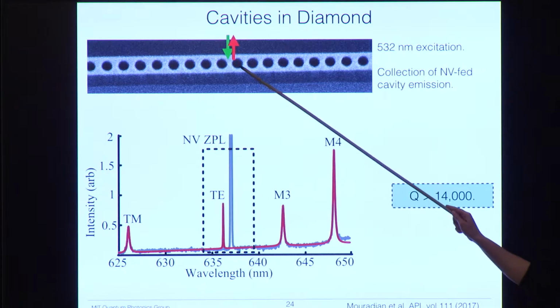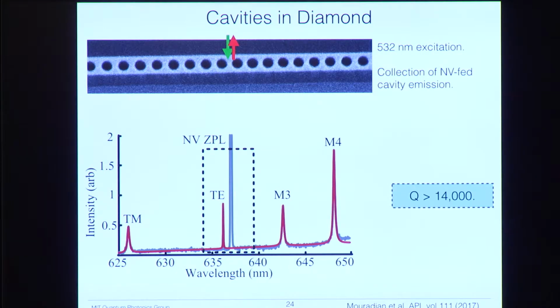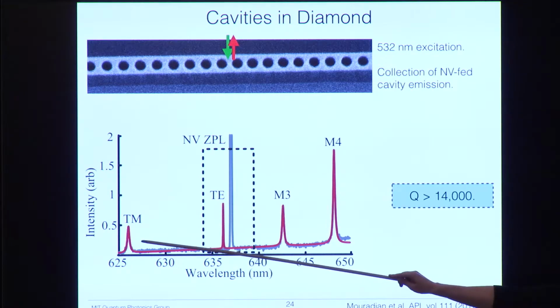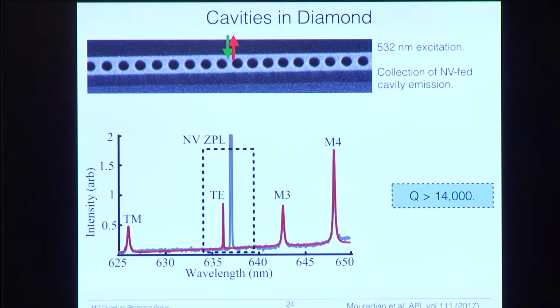So we excite with green, that's above band excitation, and we collect in red. So we collect the emission of these NV centers. And then we can look at a spectrum. What we see here is this NV-ZPL, what we saw before. This is just from the NVs, and then we see these other peaks that aren't there in bulk diamond, and those are the 4 modes of our cavity. So the first order TE mode, which is the one that we optimize for, a TM mode, and then 2 higher TE and TM modes with modes isolated in the mirror region.